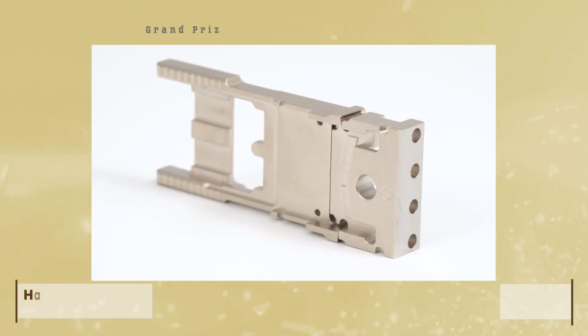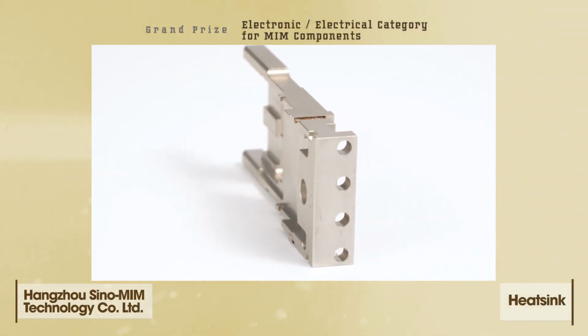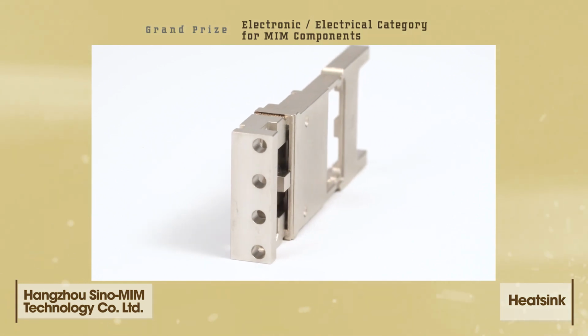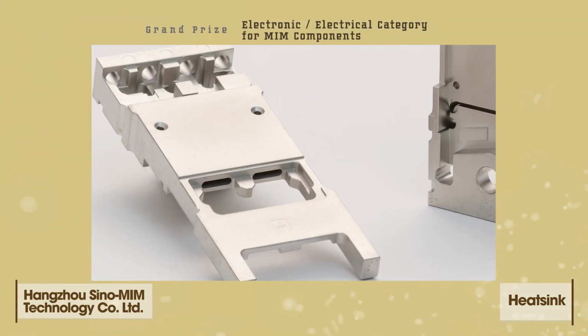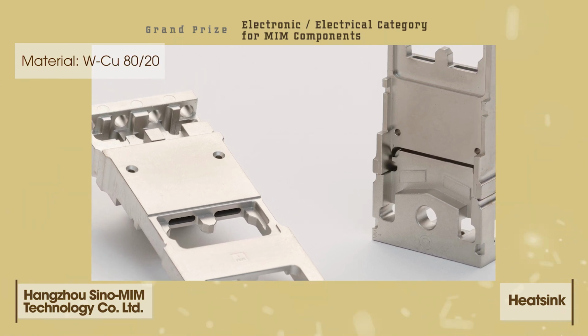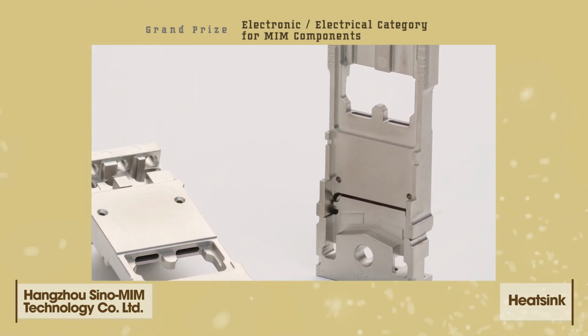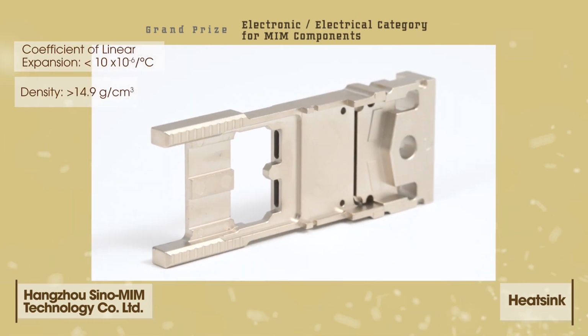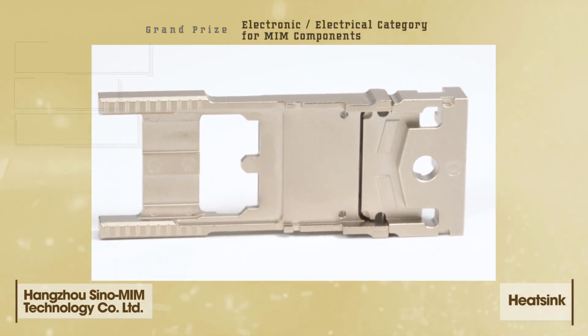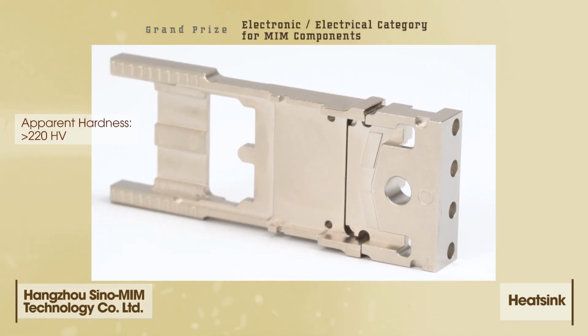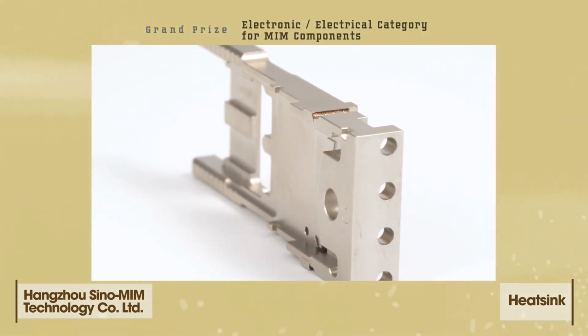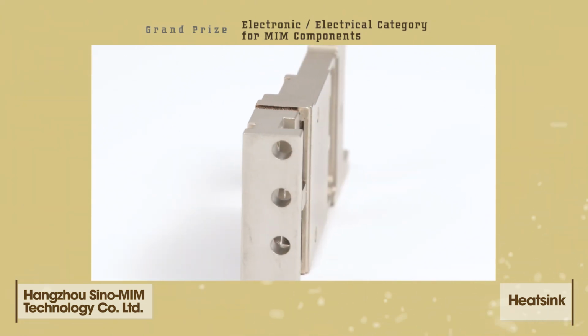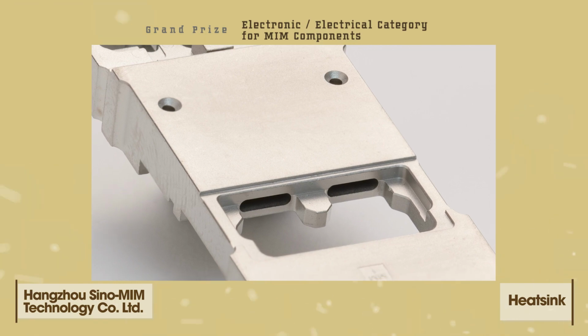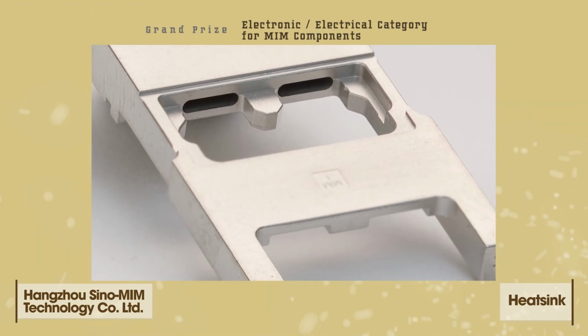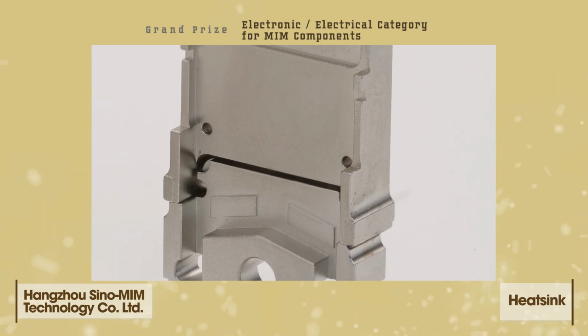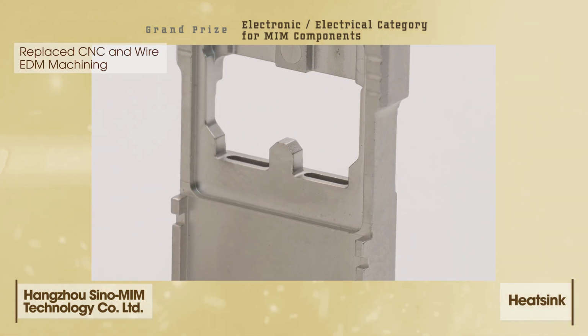Hangzhou Sino MIM Technology Company Limited received a grand prize in the electrical category for MIM components for a heatsink. This heatsink is used in an optical communication 5G base station photoelectric module bracket for heat dissipation. The part is made from an 80 tungsten, 20 copper duplex pseudo alloy. The material has strict requirements for the coefficient of linear expansion, thermal conductivity, density, and apparent hardness. The feed material is a nano-grade metal powder, so the mold requirements are very high. The feed material contains a low-temperature wax, and the molding process requires a special screw. The design has one mold with two cavities. Solvent debinding is used, and sintering is performed using a hydrogen atmosphere.